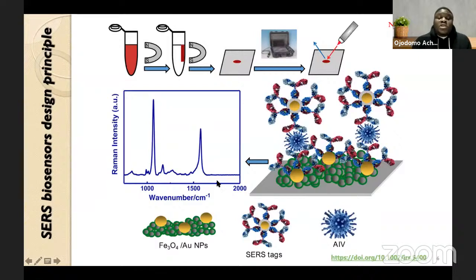The correlation, the indirect relationship between the analyte concentration and the Raman signal, is the fact that the more virus you have, the more sandwich immunocomplex you form, which means the more nanotags are going to be present on this SERS substrate. And the more the signal of the reporter increases, based on the amount of reporters that is going to be conjugated or trapped in the sandwich nanostructures.